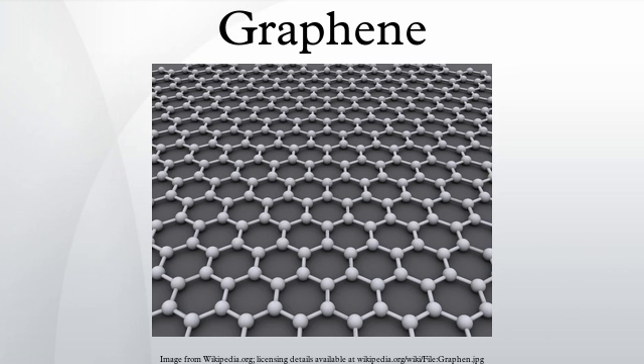Supersonic spray. Supersonic acceleration of droplets through a Laval nozzle was used to deposit small droplets of reduced graphene oxide in suspension on a substrate. The droplets disperse evenly, evaporate rapidly and display reduced flake aggregations. In addition, the topological defects, Stone-Wales defects and C2 vacancies, originally in the flakes disappeared. The result was a higher quality graphene layer. The energy of the impact stretches the graphene and rearranges its carbon atoms into flawless hexagonal graphene with no need for post-treatment.